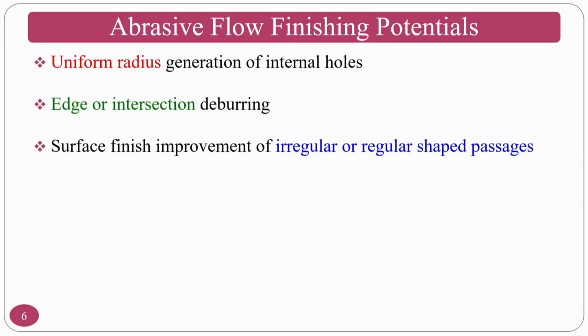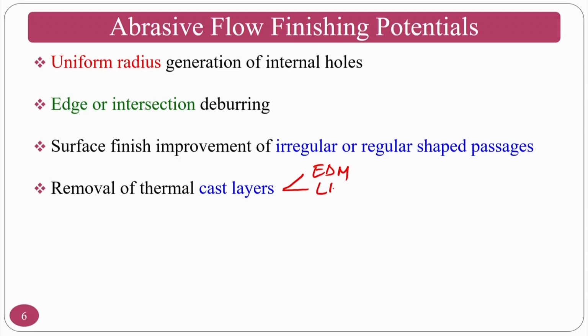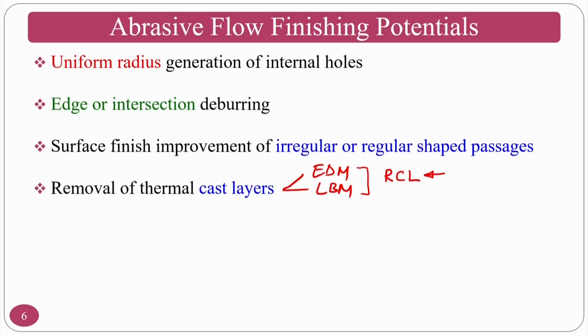Surface improvement of irregular and regular shaped passages can be achieved, along with the removal of thermal cast layers. Whenever you use thermal processes like EDM or laser beam machining, a recast layer will be formed, which we have seen in the previous classes. This recast layer is not good for practical application because it is a brittle layer, and thermal cracks will be there. In practical use, this recast layer will go off, leaving eccentricity and causing a lot of noise. That is why it has to be removed before you put it into practical applications.